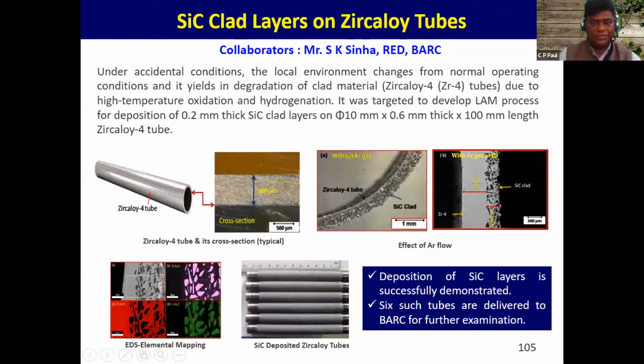Another beautiful example of deploying the additive manufacturing process to deposit high performance material. We all know that in Japan, when the Fukushima accident happened, after that there is a lot of thrust to have more and better safe reactors. And people are asking us to deposit a 0.2 millimeter thick silicon carbide clad layer on this tube of zircaloy. And this zircaloy tube is 10 millimeter diameter, 0.6 millimeter thick. You see, on a 0.6 millimeter tube, we are depositing 0.2 millimeter over that.